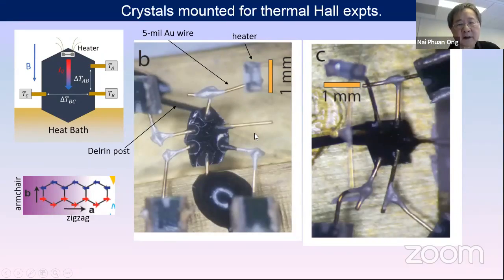And the way we mount it for Hall effect is that both the heater shown here with the orange bar, as well as the thermometers are heat sunk to the heat bath, right, by thick gold wires that you see sticking out. And so you never attach the thermometer to the crystal. It's always sitting off to the side and supported by Delrin posts so that it doesn't shunt too much heat away. And for this particular crystal, the field is applied along the A-axis. And here the crystal is being tilted at an angle, so the field is off the alignment with the layer. And again, here's the cartoon. The B and C thermometers measure the thermal Hall signal, whereas the A and B thermometers measure the diagonal kappa XX signal.